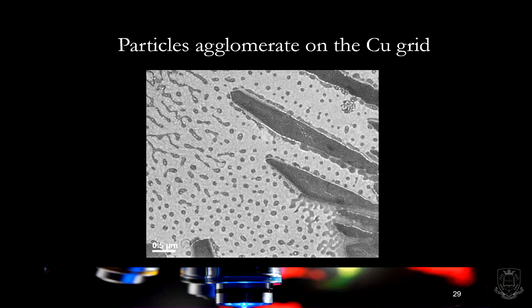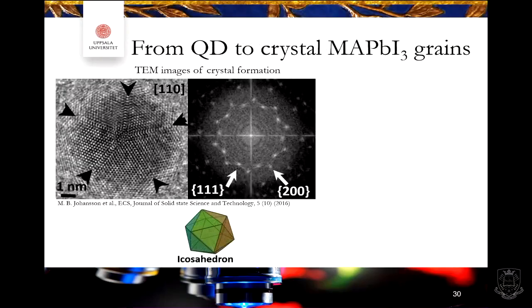What I was also able to observe in my first test was that because of the energy of the electrons in transmission electron microscopy, the energy from the actual measurement creates effects when you look at it. So I could see how particles went together and formed larger crystals, and then they continuously kept forming. This is an example of what I saw. Here you actually see a quantum dot. In our solar cell group we are also working with quantum dots, and this is an example of an icosahedron, with 5-fold symmetry, and 5-fold symmetry is also close to quasicrystals, where you usually also have this 5-fold symmetry.